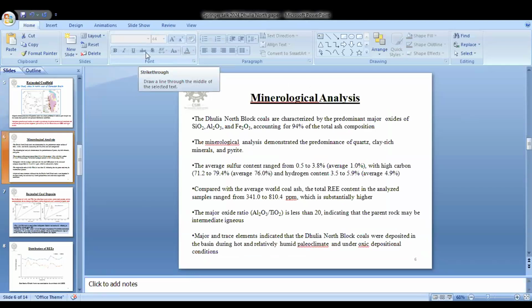What we found out was that this particular coal block, we did a thorough in-depth analysis of at least 15 samples we collected, varying in depth, and we found out that it consisted primarily of major oxides of silicon dioxide, aluminum oxide, iron oxide, which totally accounted for 94% of the total ash composition.